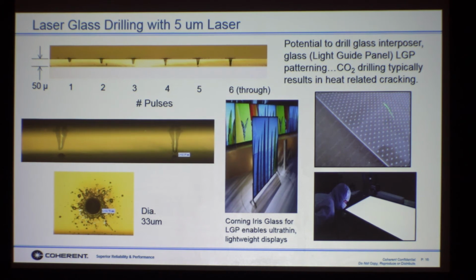These are all made with CO2 lasers today, but CO2 lasers in glass tend to crack the glass. With the CO laser, because again, the penetration is more controlled, we're able to drill very small holes. This is 33 micron diameter holes, and we're able to control the depth of the holes. So shown here are different sequential holes drilled with 1, 2, 3, 4, 5, and then 6 is finally a through hole in a 50 micron piece of glass. So very controlled, very stable holes. You can see there's no microcracking. It's very difficult to do, if not impossible to do with CO2 lasers.